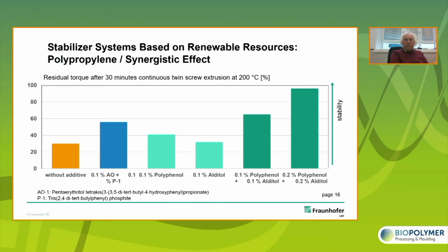If we add polyphenol alone, we see an improvement against the non-stabilized material. However, if we have a low concentration here, 0.1 only, it is not as good as the classic combination of AO plus P1. If we add alditol only, then we have a slight improvement only. The huge leap forward is by combining polyphenol and alditol at the same concentration. And we reach values of 60% or even more.